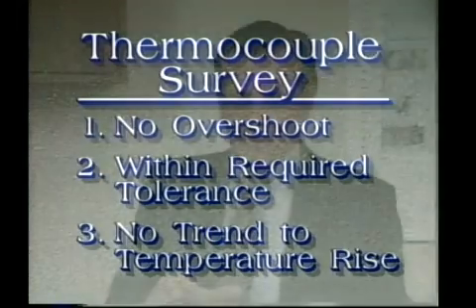In certain instances, it is imperative that the survey be conducted for a longer period of time if the thermocouples, at the end of the normal 30-minute time frame, are still increasing in temperature, because in long temperature soaks, such as 4 or 5 hours, the temperature could settle out at a temperature which could be 5 to 10 degrees higher than that which is indicated in a short-ended survey.